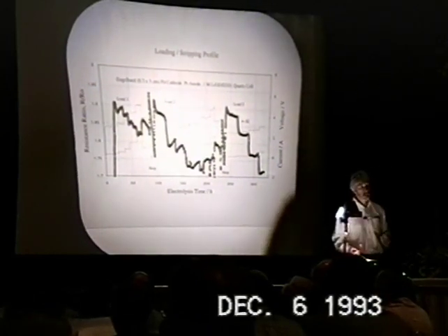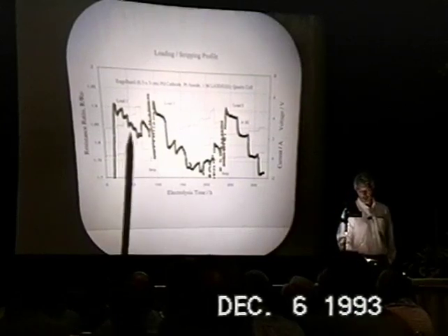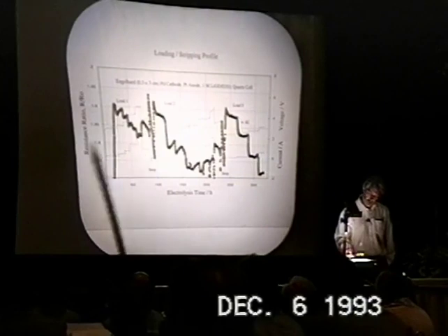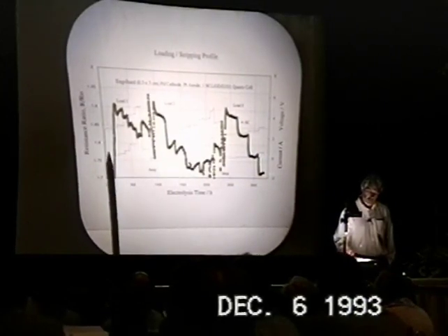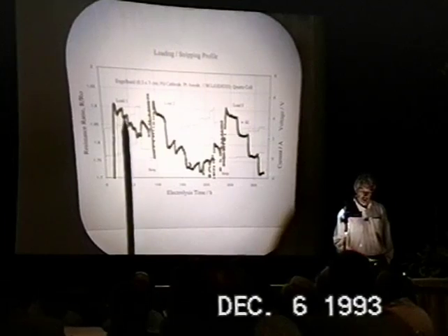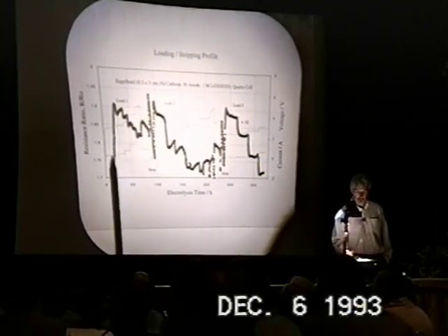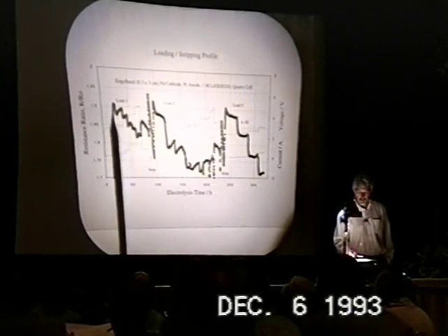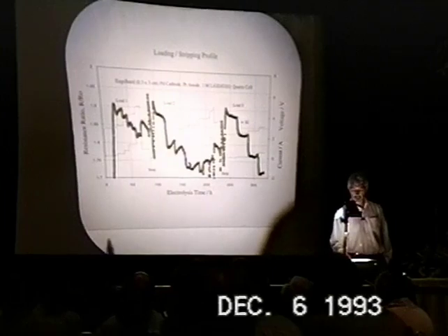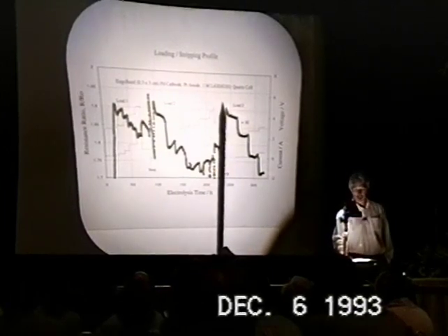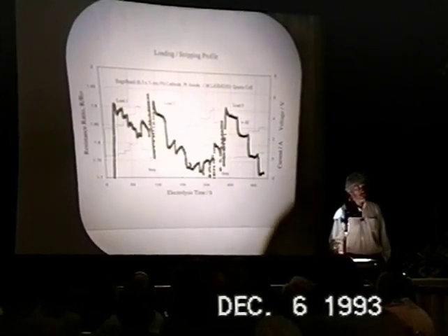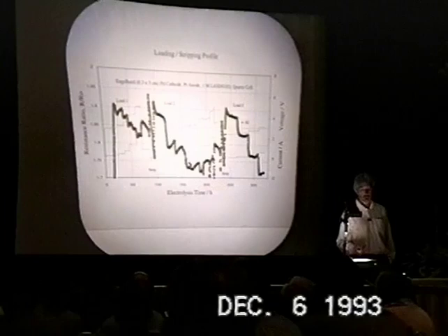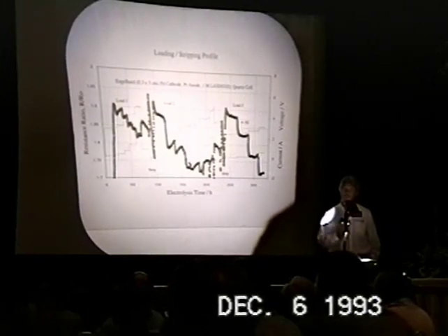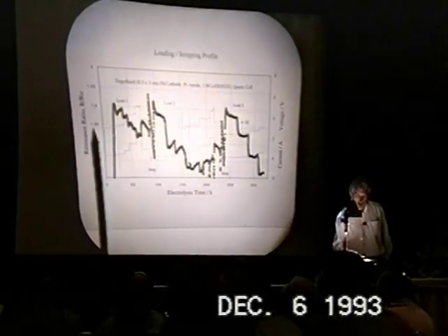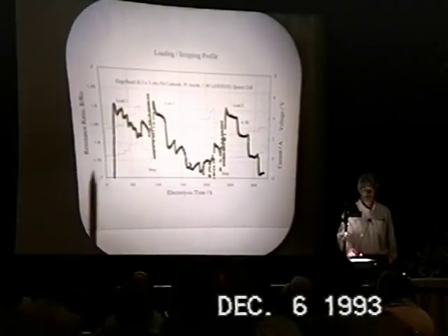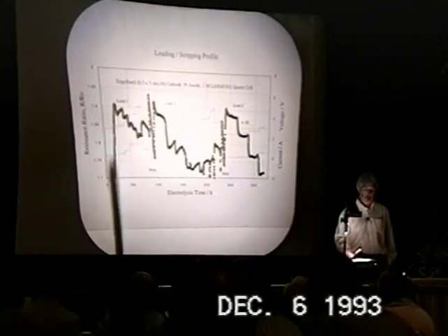The second point I was going to make is additives. Here, data presented by Alan Hauser previously. The yellow curve, loading through the maximum, then each of these steps indicate the time at which the current density has been increased. But what you can see on the first cycle, a strip here, the second cycle, a strip and aluminium addition, the third cycle, is that prior to aluminium additions, in every case when the current was increased, the resistance ratio first decreased, indicating improved loading, and then slowly with time the resistance ratio will head back up, indicating the cathode is deloading.